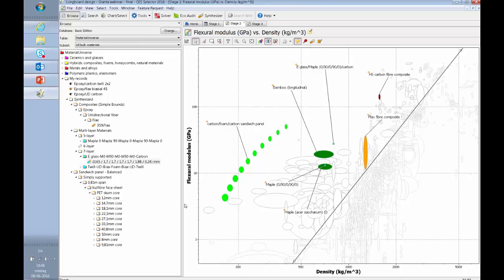I decided to create another 7-layer layup, and I'll show you that here, where we have carbon fiber twill as the outermost layer, UD carbon fiber, and then flax biaxial fabric. Those three layers together create the face sheet. Then there's a foam core, and then you have the same face sheet on the other side. Now this is really based on experience, and I performed a hand calculation to make sure that the bending stiffness of this configuration would be the same as the reference board.